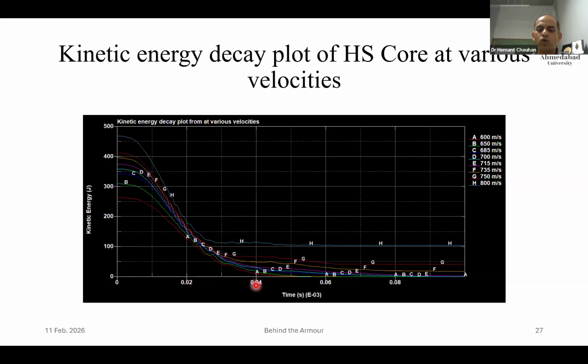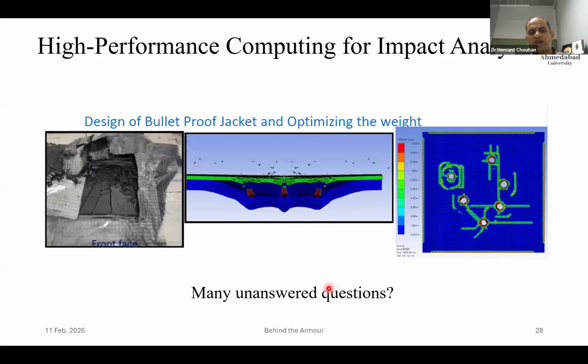So we see that after 0.04 times 10 to the power minus 3 of a second, the 800 meter per second bullet will still have more than 100 joules of energy. This is still a lethal one, sufficient to kill or significantly damage a human. Whereas as we go down, the kinetic energies are nearly zero. So for 715, it is zero. So we are having a very good model. For this case, we have used LS Dyna. Abaqus is equally good, but for bullets and these kinds of events, LS Dyna is preferred. So we have been into that.